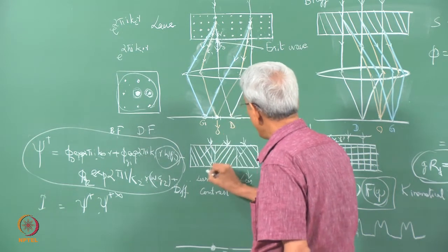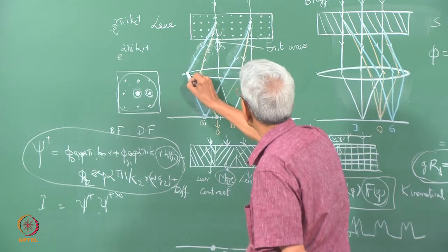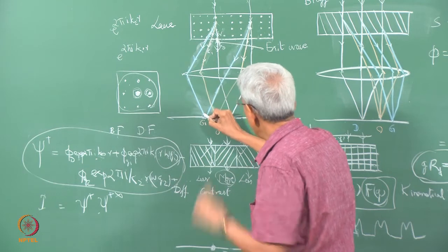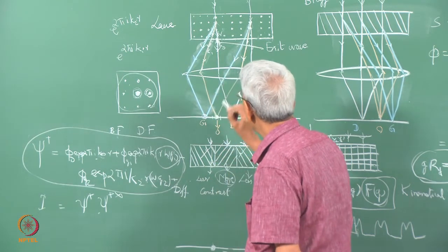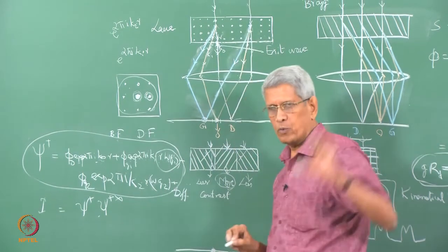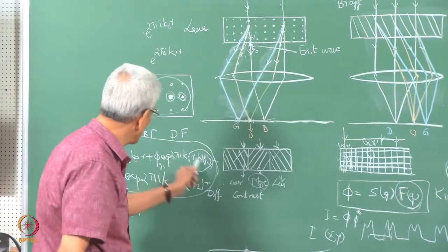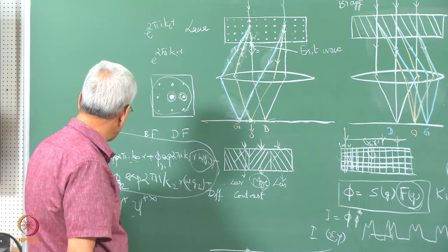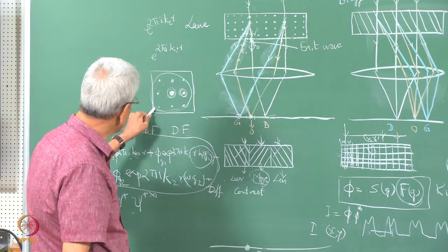In the case of a bright field or a dark field, we are looking at only some specific direction, which means the wave scattered only in this direction gives some contrast in the image, but that does not contain complete information about the sample, only a small part of it. In the high resolution image, the complete information is coming, because we use as many reflections as possible.